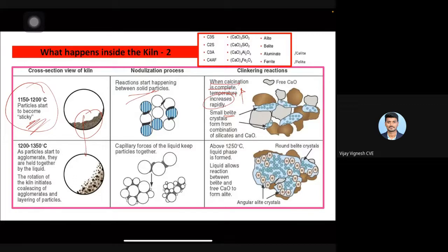So first you can see here, this is the free calcium oxide. It can react with small things, a small compound that is called belite. Free calcium oxide and these things combine together, and we can get that alite. This is the combination. Now around 1200 to 1350 degrees centigrade, this material tends to melt.